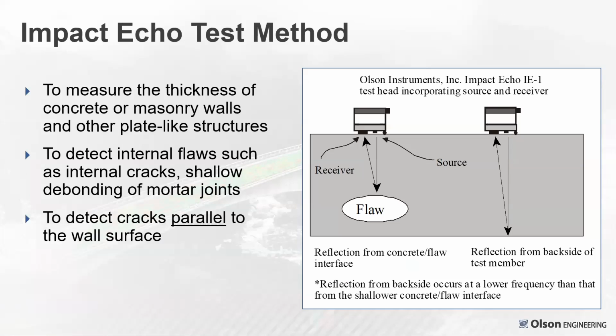So the impact echo method is shown on the right. We have a unit in various platforms that you can test with that impacts with a solenoid, good to about 12 to 18 inches in thickness, and it picks up the echoes with a displacement transducer. You can use a small hammer to see out to 6 feet, maybe a little bit more.